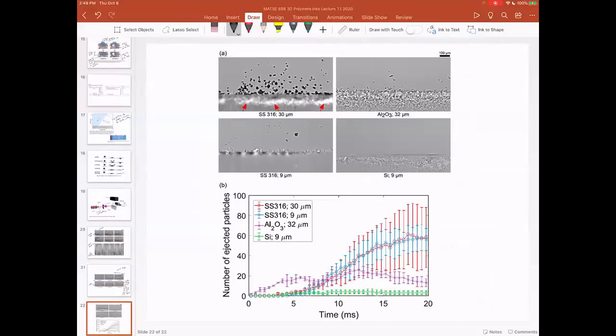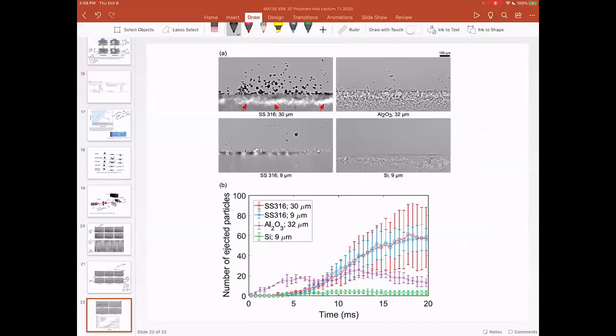And the last cool thing that I'll point out in this paper, and you're welcome to read this for all the details, is that they're looking at the number of ejected particles, and it varies depending on the particle size, the density of the particle, and the binder jetting conditions. For this silicon powder, it's not moving around very much. You can see very low ejection of particles, but for alumina and stainless steel of different sizes, you get lots of ejection of particles. And that's very interesting, that this is a chaotic process. This adds to the surface roughness. This also can influence the part quality and the anisotropy if it's not controlled.